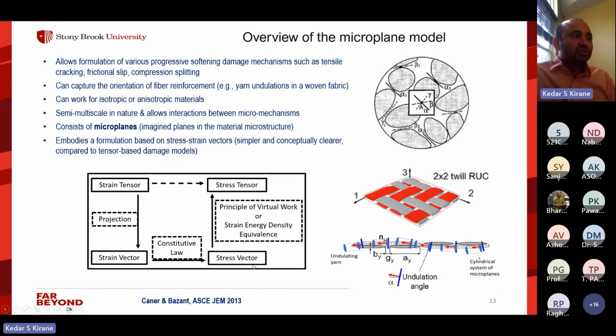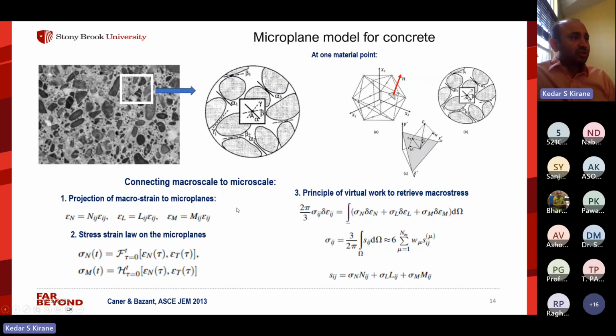And then once you get these stress vectors, you can use the principle of virtual work, or alternatively, we will use strain energy equivalence to recover the stress tensor back. So by introducing these microplanes within the model, it becomes very intuitive to define various damage mechanisms. All right. So basically the structure goes like this. You project the macro strain onto various microplanes. And this is, of course, for concrete, but we adapted this approach to composites, which I will show later. So you get these strain vectors, one normal strain vector and two shear strain vectors. Then using whatever constitutive law, you get the stress vectors, and then you homogenize these stress vectors using the principle of virtual work to get the sigma ij, which is the stress tensor.